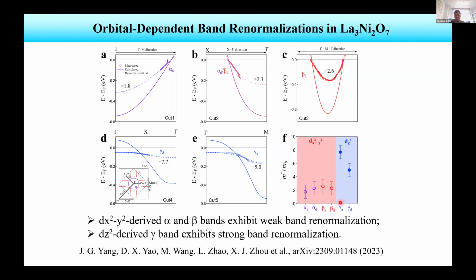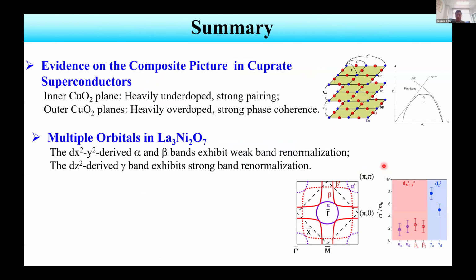By putting them together, we found that the dx square minus y square derived bands have a smaller band renormalization, between 2 and 3 in this case. But the dz squared derived bands show a much larger renormalization factor, between 5 and 7, so around 6. So it's much larger in this case. Okay, so eventually, I give a summary of my talk.